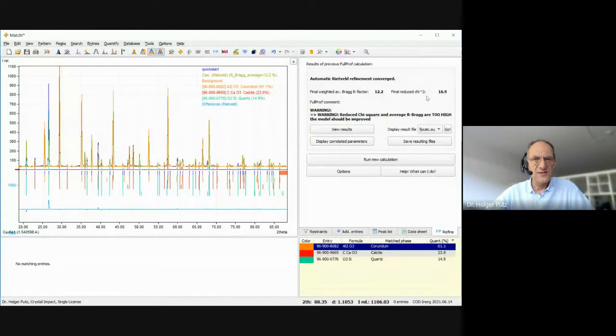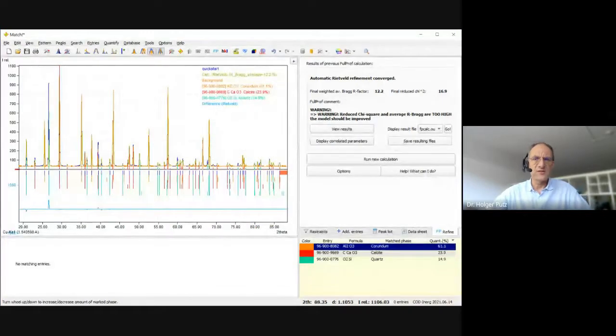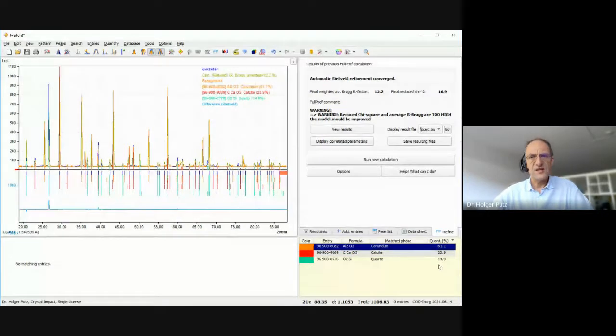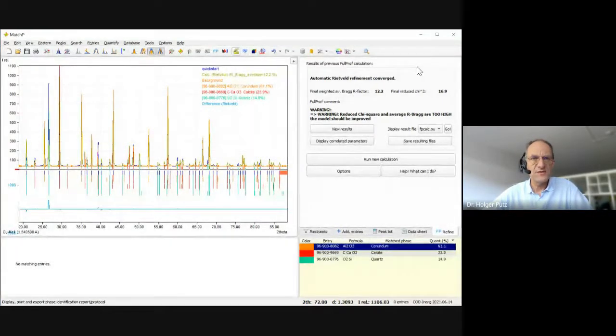with the R factor and the chi-square value. And here you can see that the calculation has now converged. And now the amounts given here below are no longer taken from the reference intensity ratio calculation, but from the actual Rietveld refinement calculation. So at this point, our analysis is now finished. We have a qualitative and quantitative result, and we can summarize it in the report that I can display using this button here.